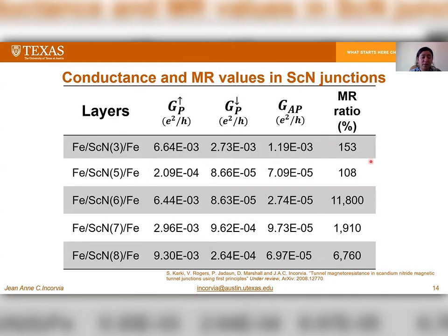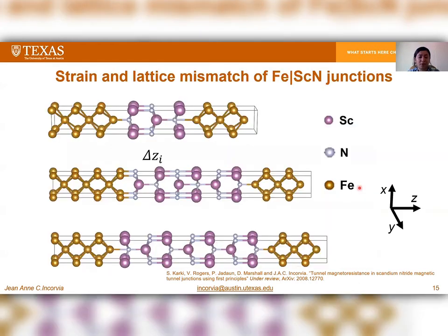Further on, we looked at the parallel and anti-parallel conductance values and also the MR ratio of the junctions. We see we get a very high MR ratio of about 12,000% for a 6-layer system and as low as 100% for a 5-layer system. So we wanted to further study why there is a variation in our MR ratios. And we think one of the reasons could be the lattice mismatch between iron and scandium nitride.